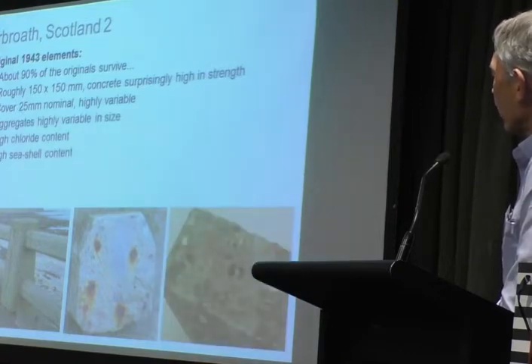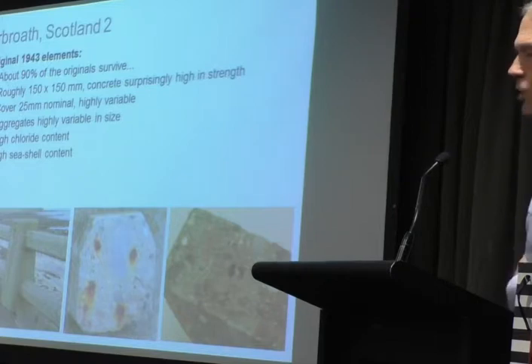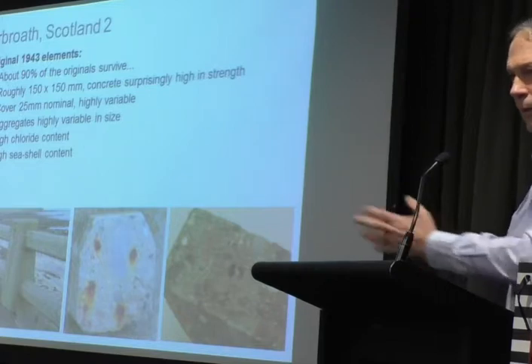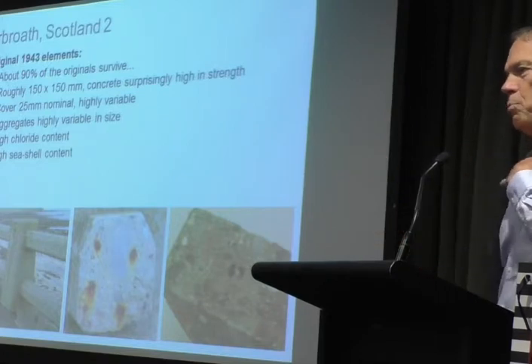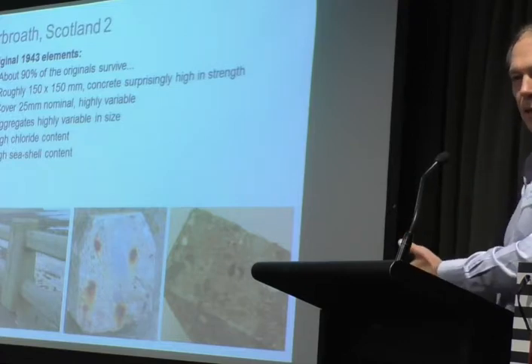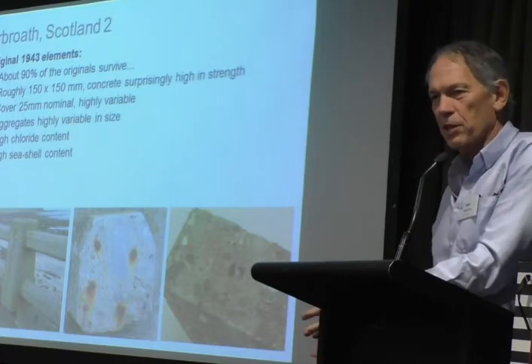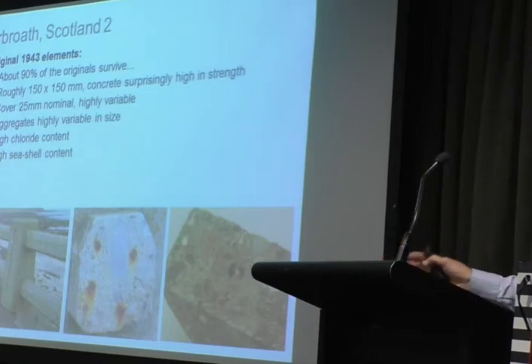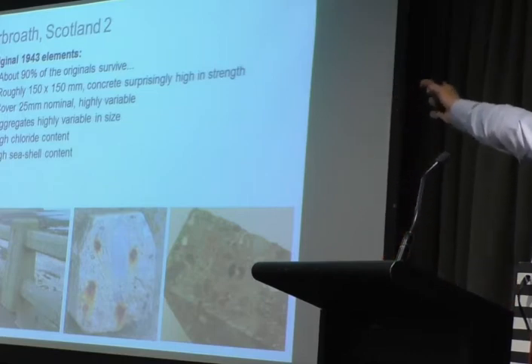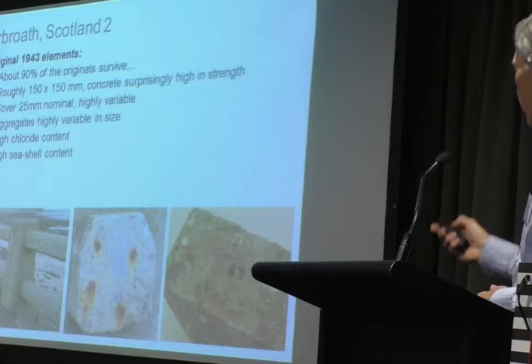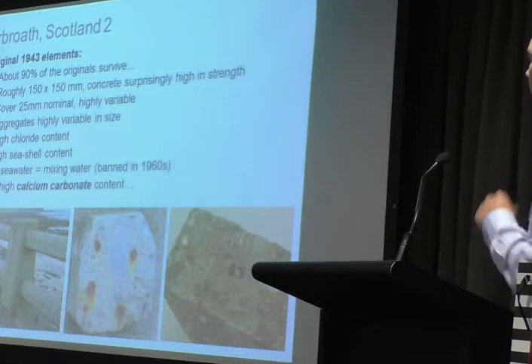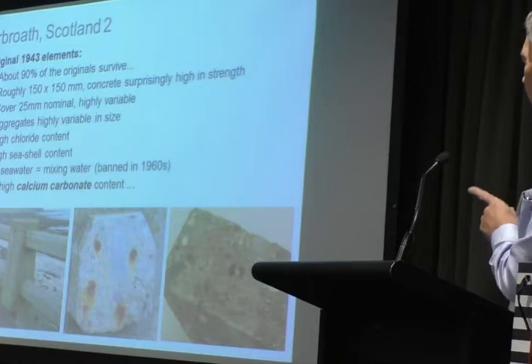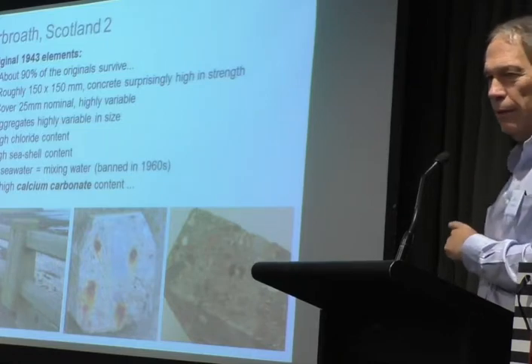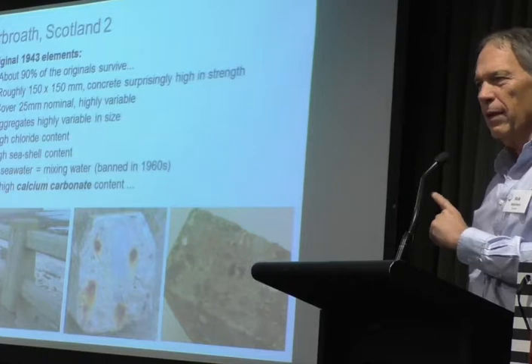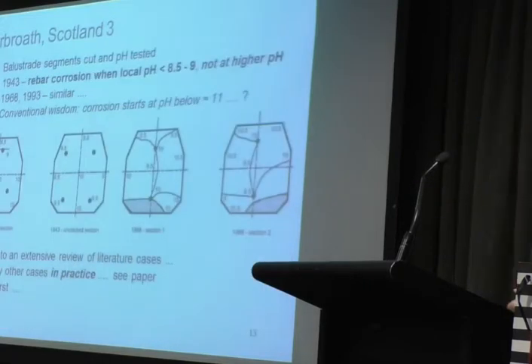And when we looked more closely, what did we find? Seashells in the aggregate, in the concrete. That tells us pretty well that they just used the local seashells, this local sand, and mixed it with seawater, so it was full of chlorides right from the beginning. And yet, it lasted 60 odd years. We know that seawater was banned in the 1960s, but it does tell us there's a high calcium carbonate content in that concrete. And that sort of worried me.